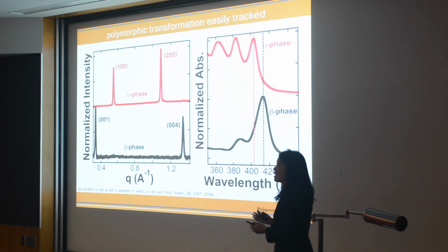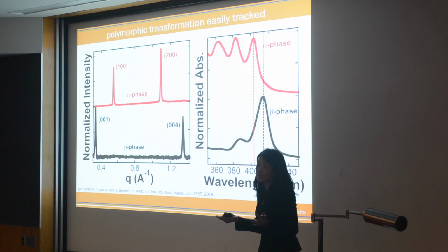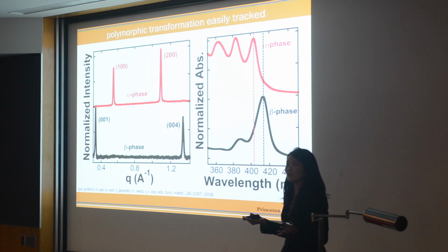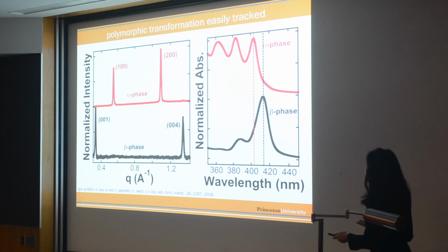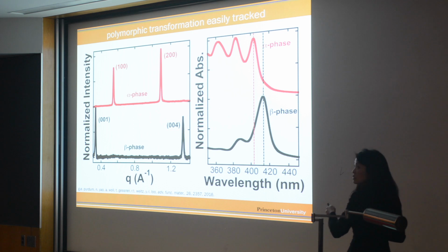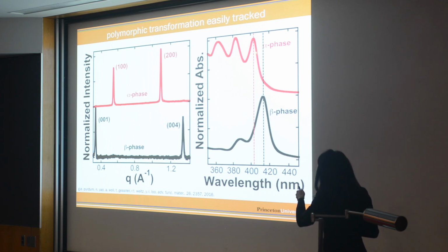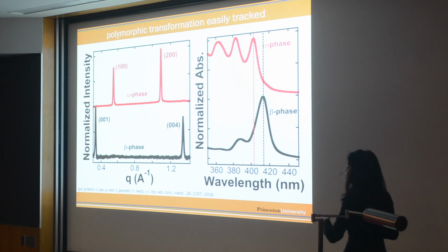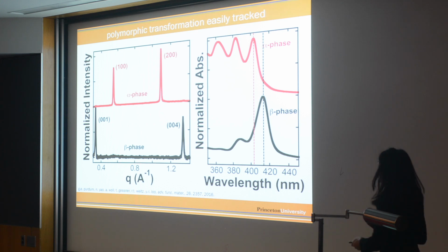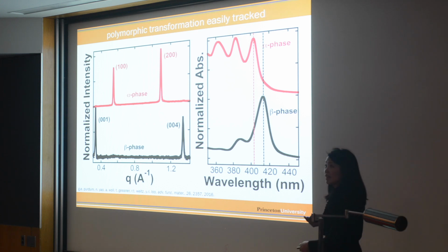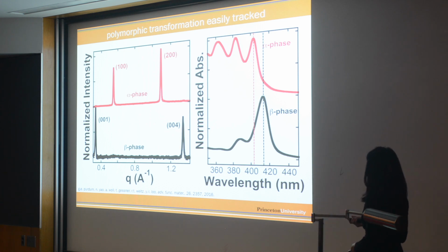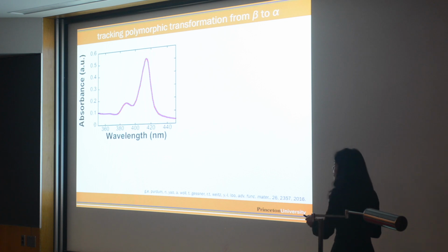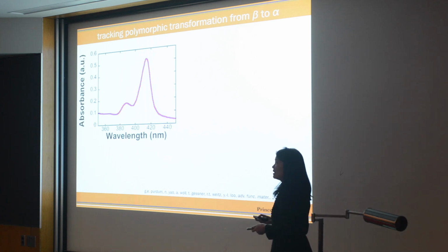But X-ray diffraction is not very convenient. We only get beam time about 4 times a year, and so we have a lot of experiments we want to do. We were lucky in the sense that we see absorbance differences in UV-vis, so we can do that in-house. The alpha phase's unique fingerprint is very different from the beta phase's unique fingerprint. So now we know this, we can carry out a lot of these experiments in-house using the UV-vis spectrophotometer.